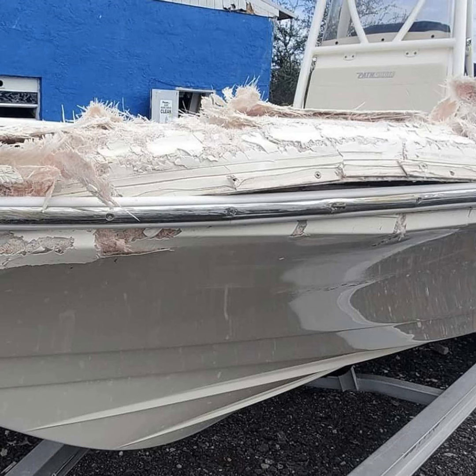Then you can measure the thickness of how much glass you've ground out, and replace that glass from the front side by applying fiberglass layers. You can either make them get bigger and bigger as they work through your bevel, or sometimes I'll just make them all the same size and stack them up and have to grind a little more on the outside edge. It doesn't really bother me to do that, because once I'm slinging dust, I'm slinging dust. But that's probably the easiest way that you could repair a hole or something like that.